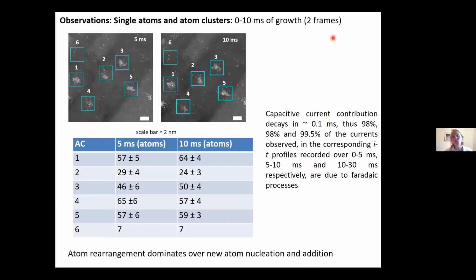And again, with all the images we've created for these different timestamps, we've tried to look for emerging patterns across the surface. As I said, there is just so much data to look at. So here we image the surface after 5 milliseconds of growth, and we pick these 6 zones. Then we did a further 5 milliseconds of growth and looked to see what happened in these zones. And for each one of these zones, we atom counted.